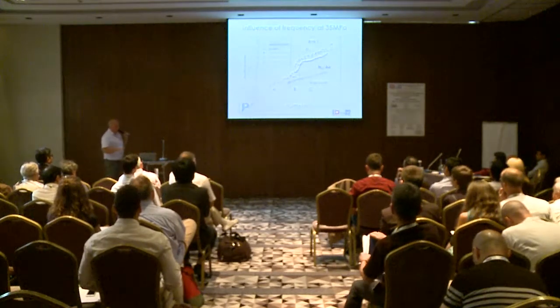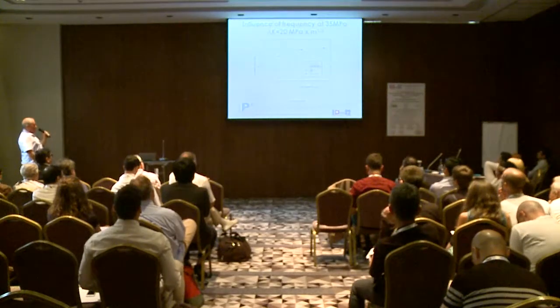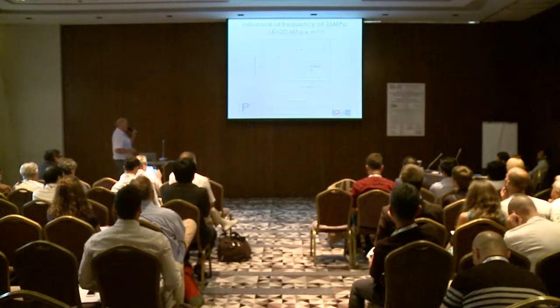Typically, such a saturation was not observed in a martensitic material. So this is another representation of this frequency effect for a selected value of the stress intensity factor range of 20 megapascal square root meter.